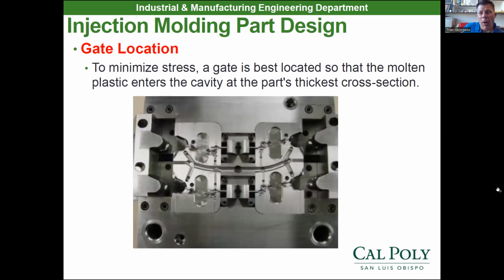Now, when you're designing a mold or tooling for the part, you always want to gate in or basically fill the mold in the thickest cross section. So you always fill in the thickest cross section, and that helps with cooling and the solidification of the actual part right there. So always gate into the thickest cross section. And we're really just gating in to the thick center of the part. The reason I didn't gate into the top, I wanted the top to be real smooth on the part. So we're gating into this backside where we're going to face that off and drill and tap that side of the part. So you'll never even see where the gate was on this part.